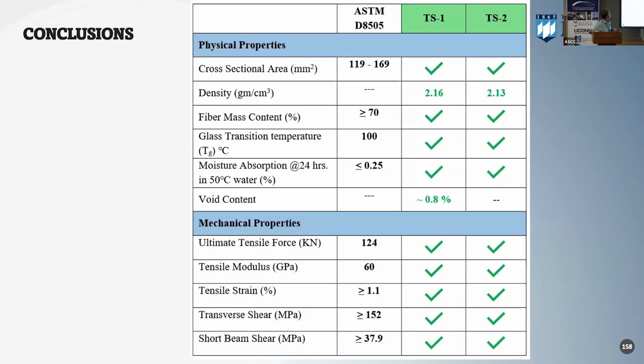Next one. So here I have a summary of kind of the grades that we're getting. Both systems make all the checks, okay? And I put a comment on the void content we measured in one of the bars. We couldn't measure that in the other one, but again, that void content was within what we would expect in typical bars. Again, this is what qualifies a bar.